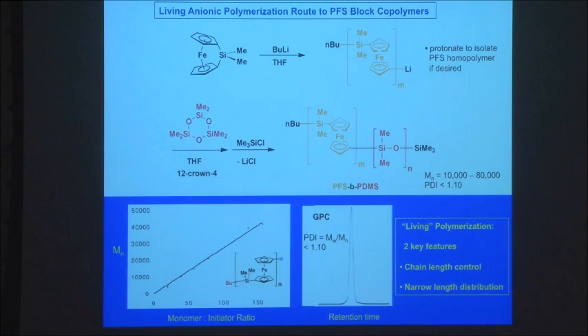So the polymer chains all start to grow at the same instant, and they grow until the monomer is used up. And so the polymer chains you get all have essentially the same length. Here's a GPC trace for the polymers that you can make using this method, and then you protonate them deliberately to isolate the polymer. And you get polydispersity indices very close to 1. If you remember back to the GPC trace I showed earlier, which was really broad for the thermal and catalytic methods for making the polymers, where there's spontaneous chain termination, for example, you get a much broader molecular weight distribution. So you get very well-defined materials using this process. So you've got these two key features of a living polymerization. You can control chain length, and you get narrow length distributions.